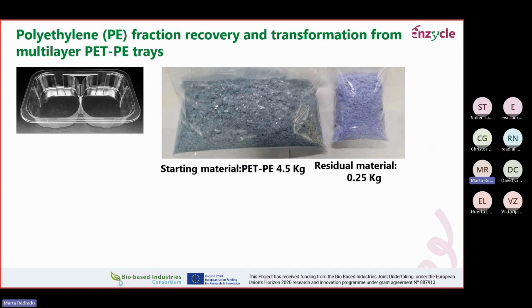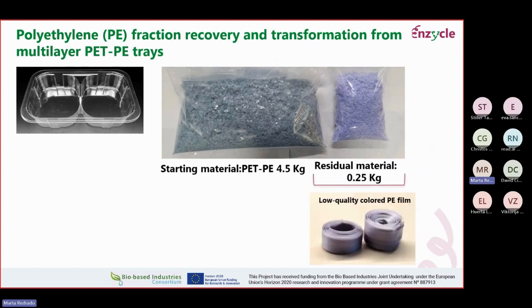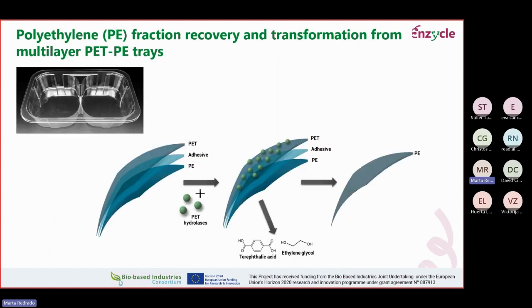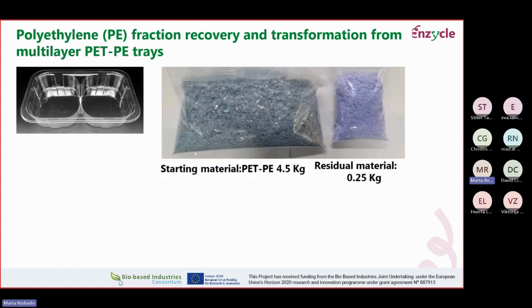We started with, for instance, 4.5 kilos of PET polyethylene material, and with our enzymatic reaction in our reactor, we were able to eliminate virtually all the PET present. So we would recover 250 grams of residue, which contains mostly polyethylene. And I say mostly because even if we virtually eliminate all the PET, you always have some residue of PET there, which is a bit annoying, but well, it is what it is. Probably some of the PET is not really accessible by the enzyme, or maybe the presence of the adhesive is also inhibiting the accessibility of the enzyme. We don't know yet, but so we obtain this residue.